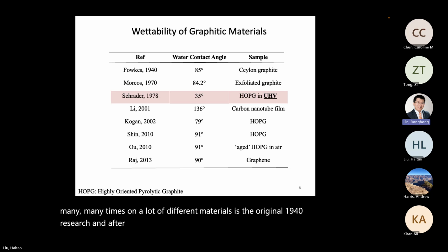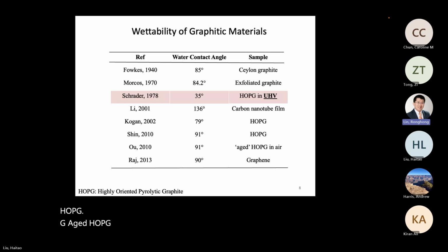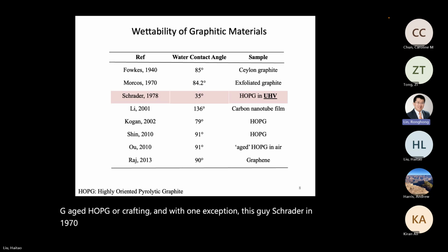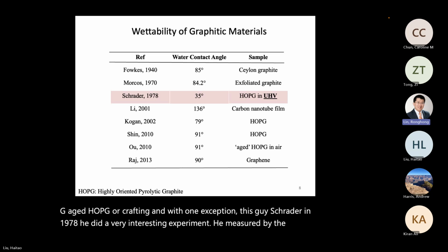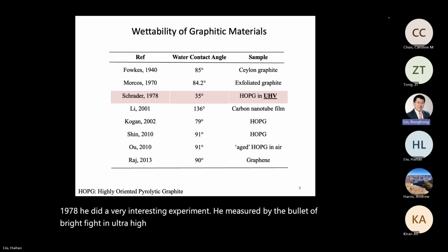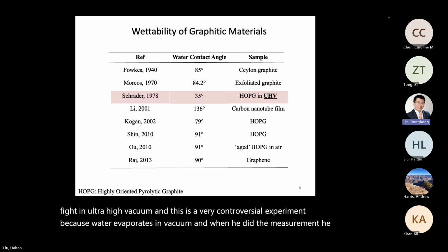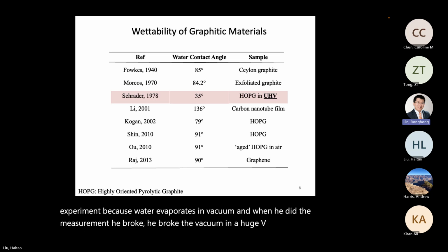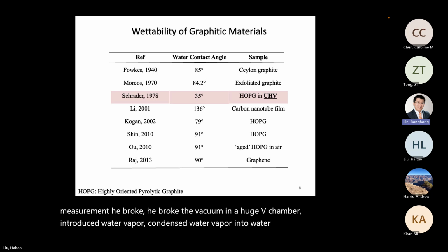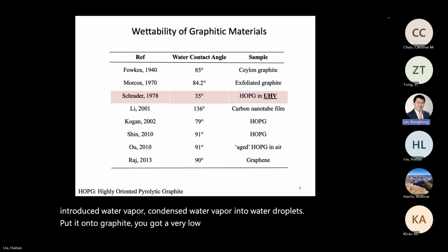And after that, there are all kinds of carbons being measured, HOPG, aged HOPG or graphene, and with one exception. This guy, Schrader, in 1978, he did a very interesting experiment. He measured the wettability of graphite in ultra-high vacuum. And this is a very controversial experiment because water evaporates in vacuum. And when he did the measurement, he broke the vacuum in a UHV chamber, introduced water vapor, condensed water vapor into a water droplet, put it onto graphite. You got a very low angle.